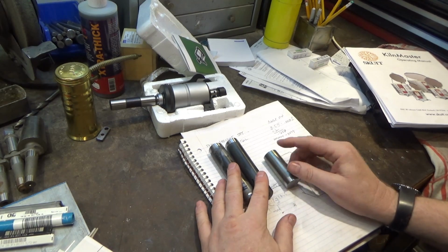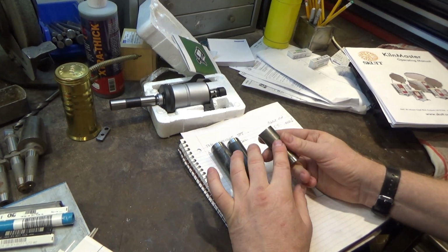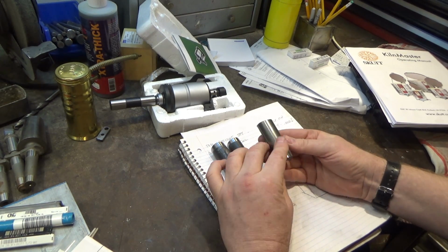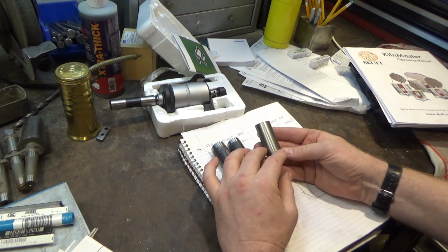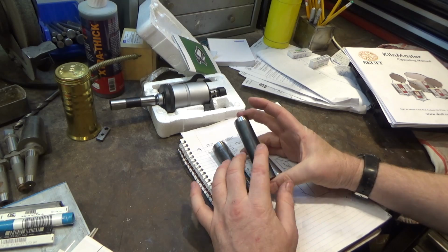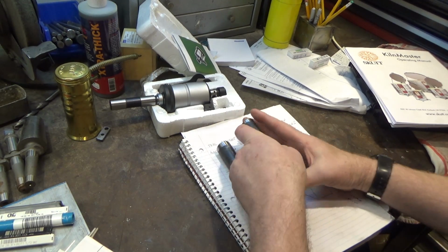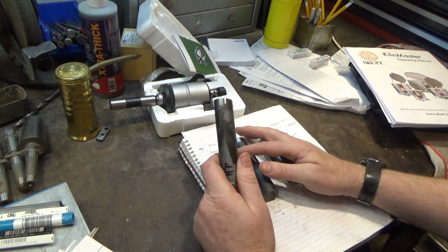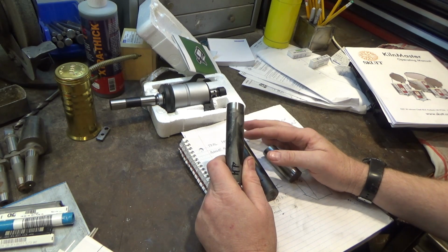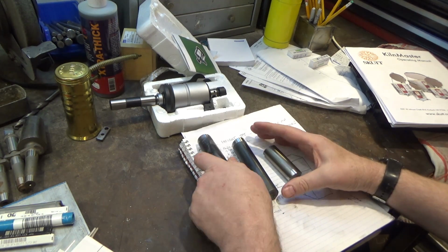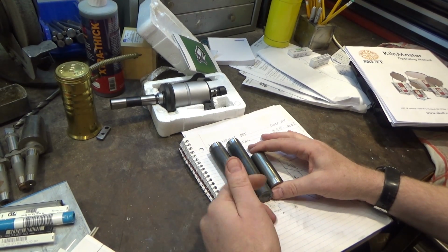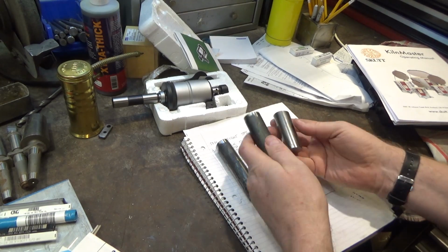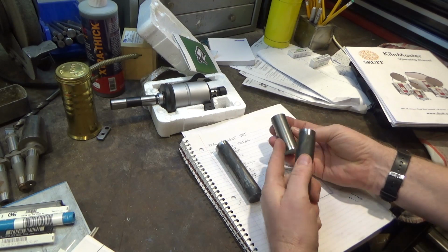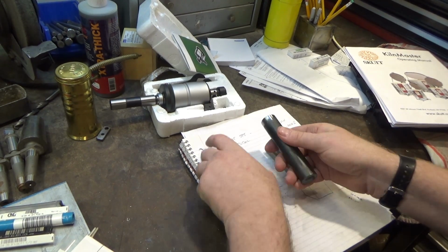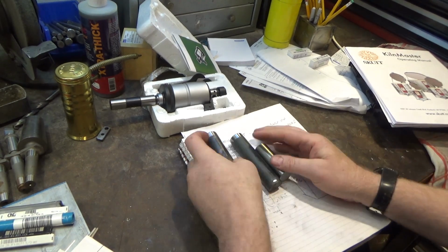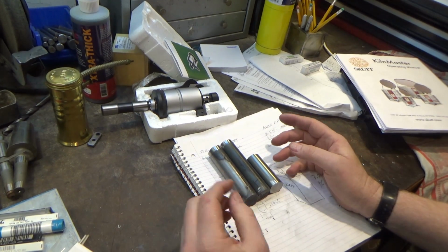Alright, so here are the three pieces of metal we're going to work on. This is an untreated 4140 chromoly annealed piece as delivered from the vendor, roughly Rockwell C hardness of 13. This is a hardened and tempered piece, tempered to about 39 Rockwell C. And this one is the heat treated only, and it could be between 54 and 59 Rockwell C hardness. Right off the bat, besides the obvious mill scale, I noticed that the normal chromoly, the annealed version, has a different ring to it than the hardened ones. So next step is to head over to the lathe and do some cutting.